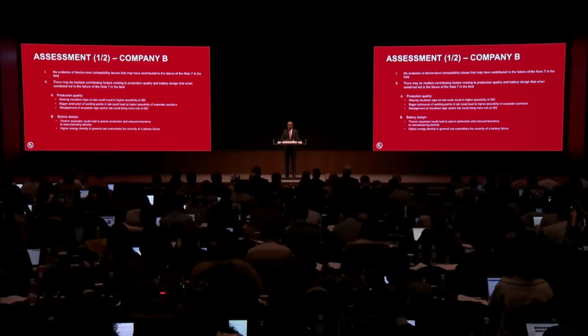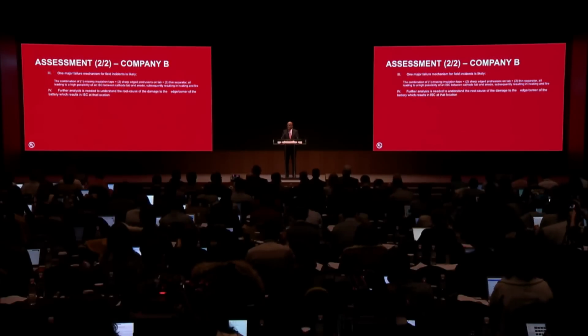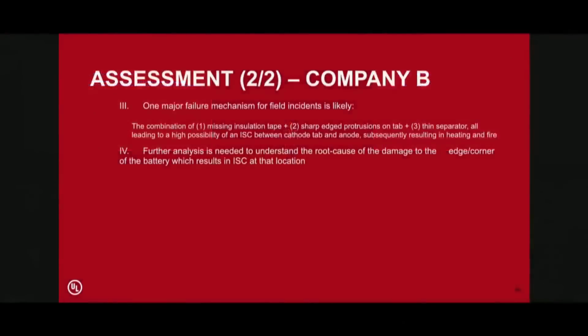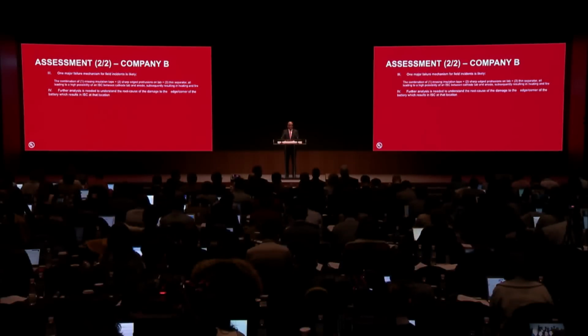Our assessment further suggests that one major failure mechanism for field incidents is likely, and that is a combination of missing insulation tape and sharp edge protrusions on the tab, combined with a thin separator, with all three leading to a high possibility of an internal short circuit between the cathode tab and the anode, subsequently resulting in heating and fire. Our further conclusion is that we need additional analysis to understand the root cause of the damage to the edge or corner of the battery, which results in internal short circuit at that location.